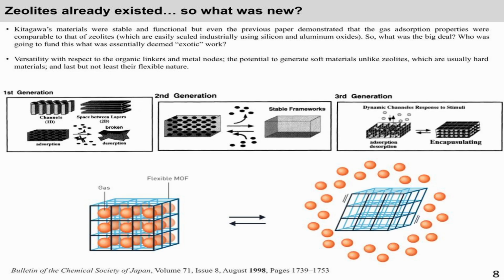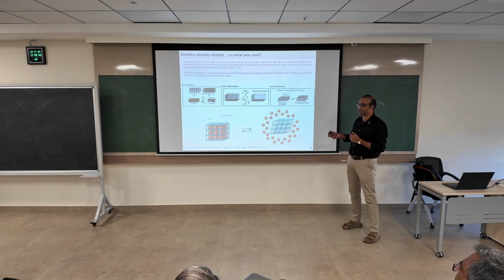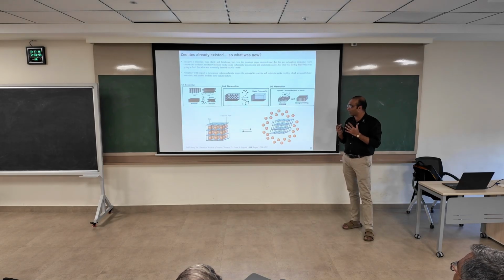So this is the first generation where you could make these layers. But when the gas is adsorbed, and then when you wanted to release it, either when it's adsorbed or desorbed, it broke apart. The gas couldn't be contained. The structural integrity of the MOF was not that strong. In the second generation, where you made these stable MOFs, they could adsorb and desorb, but they were kind of rigid.